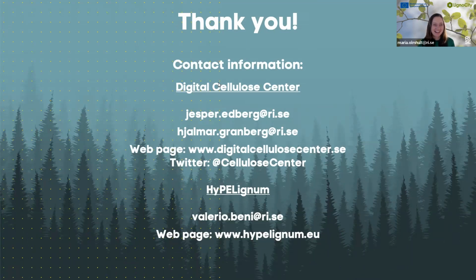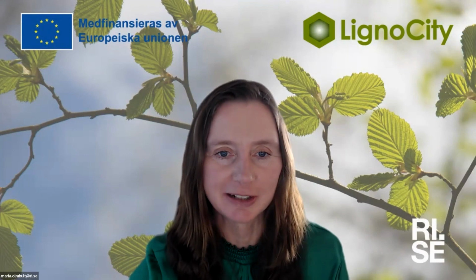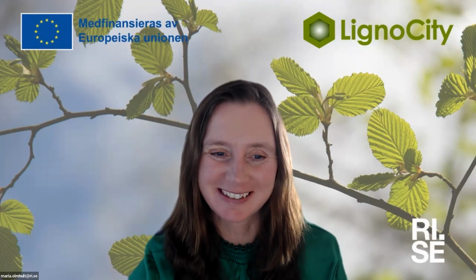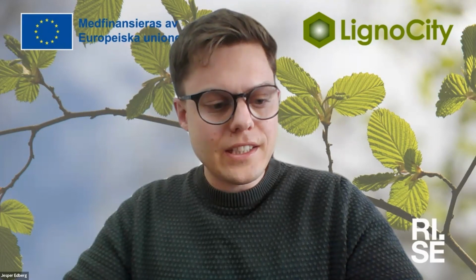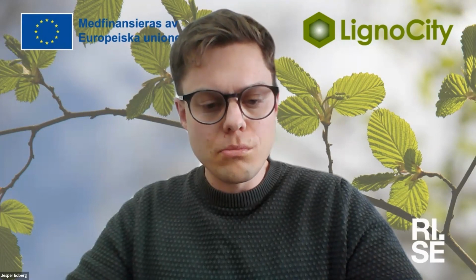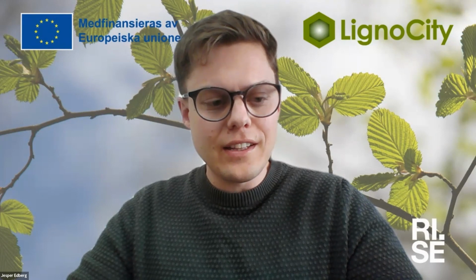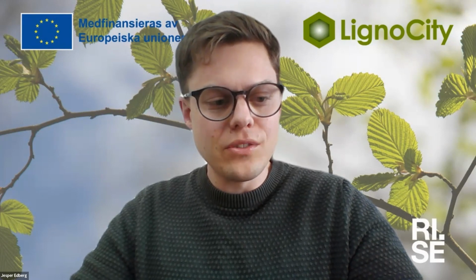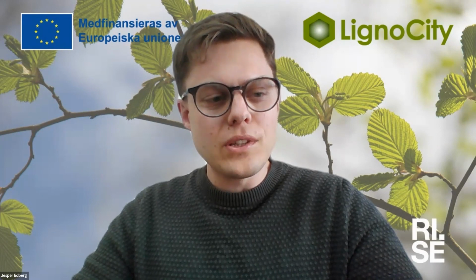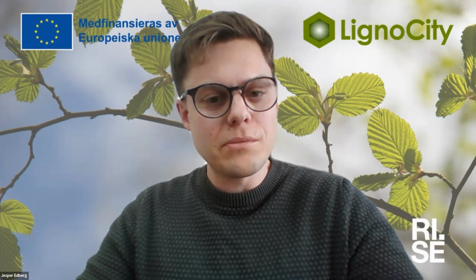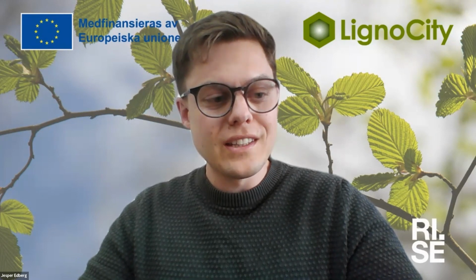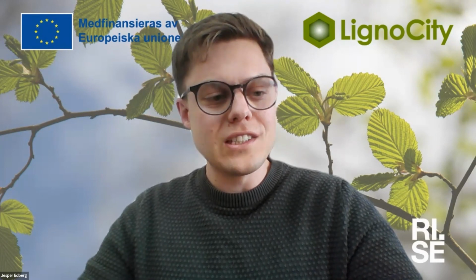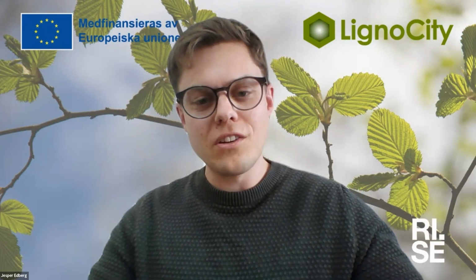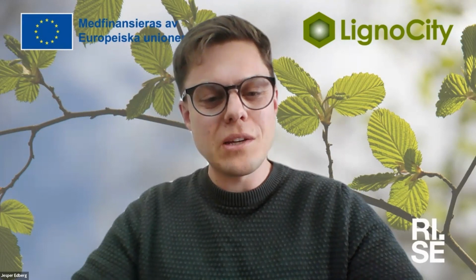So here we go. Does it matter from what wood species the lignin in the laser-formed graphite comes from? And what counter ion is used in the lignosulfonate? Yes, we have tried a couple of different forms of lignin for the laser graphitization. The one that worked the best for us was lignosulfonate, so sulfonated lignin, but it's unclear if that is because of the specific molecular structure or if it's more about that it was a molecule which was easy to form into an ink, and then we had a high quality of the prints. It's a bit difficult to separate the two.